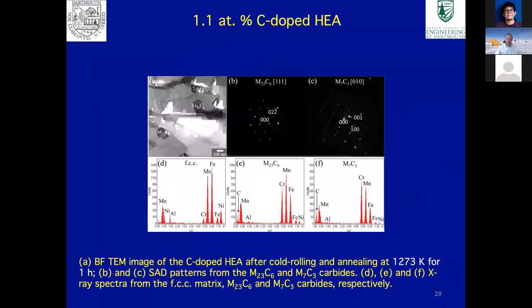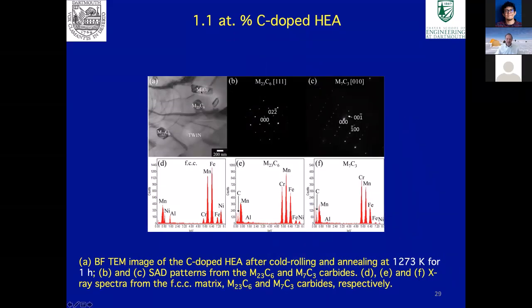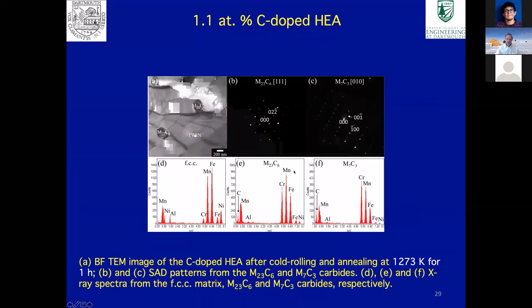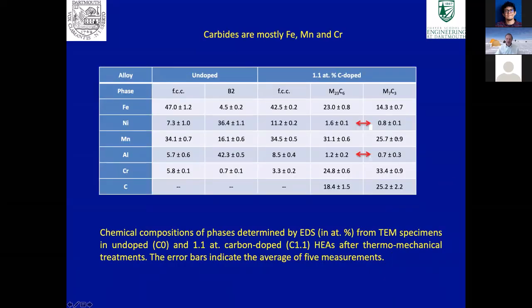And you can again identify these two different kinds of carbides in the TEM, which were identified by electron diffraction. And we also did energy dispersive X-ray spectroscopy on them, as shown here. If we look at those results, what you see for the carbides in the material is they have a lot of iron, manganese, and chromium, and very little aluminum and nickel because they're not strong carbide formers.